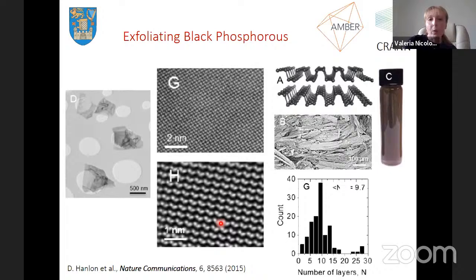What we learned as well was that we could select some solvents that really stabilized the material and really delayed the degradation. So rather than having a few minutes lifetime, we could extend it to months even. One thing that was unexpected, and this is also part of fundamental science, understanding the unexpected and using the unexpected, was that when you do high resolution microscopy on a material, this material needs to be extremely clean. If you have any residual solvent, that ends up in contaminations, and the contaminations simply do not allow you to resolve atomic resolution.